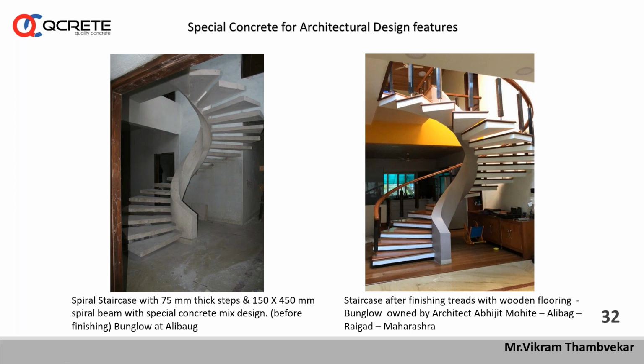Whereas from the mix design point of view, we have used only 10 mm down, meaning 6 to 8 mm size aggregate, by sieving it from 10 mm down, and of course cement content and some mineral and chemical additives. We have used it, and the steps of this spiral staircase are only 75 mm thick, only 75 mm thick. You can see here the staircase before finishing, and this other picture shows it after finishing these steps by providing wooden tops at the treads and other things, and it looks very beautiful, with a very beautiful architectural and aesthetic view also.